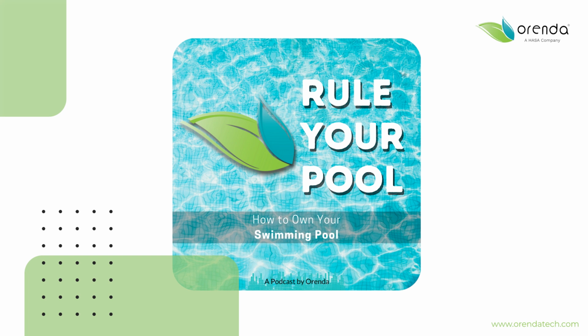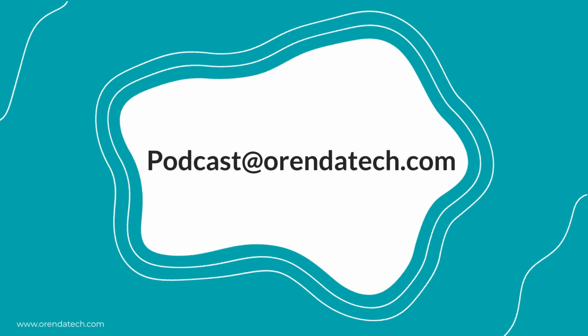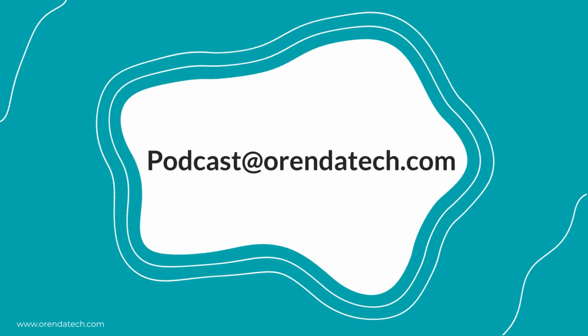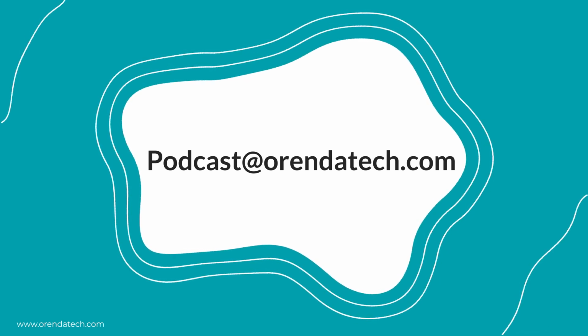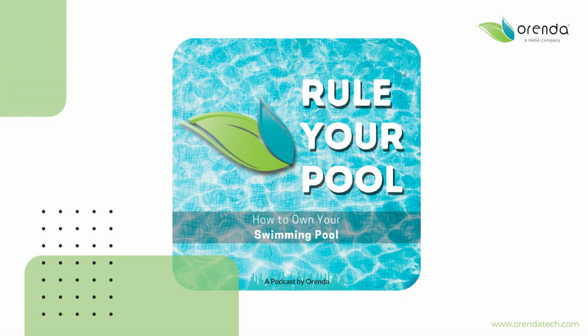Now, because we know during regular operation that the pH is going to rise, assuming you have the industry standard 80 to 120 alkalinity, like so many people do, the pH is going to rise into a scale-forming condition week after week. So scale deposits in the highest LSI places first, which tends to be the hottest places, which is going to be the heat exchanger or the salt cell or something like that. So you can get a thin layer of scale, even though the corrosion already started from the startup.